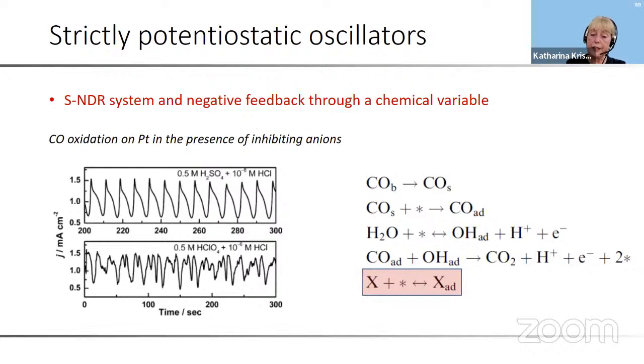Okay, finally, we have a third type of oscillator in electrochemical systems, and these are so-called strictly potentiostatic oscillators. And here you have an S-NDR system, which means you have a chemical autocatalytic system and a feedback through a chemical variable. In the case of CO oxidation on platinum, what is sufficient to drive the bistable system into oscillation, under a constant value of the electrode potential, is a reversible adsorption and desorption of some species, for example a halide ion, chloride or bromide, which inhibits the adsorption of carbon monoxide. This is all you need. And then you also obtain strictly potentiostatic oscillations.